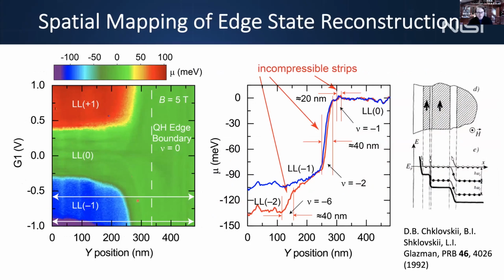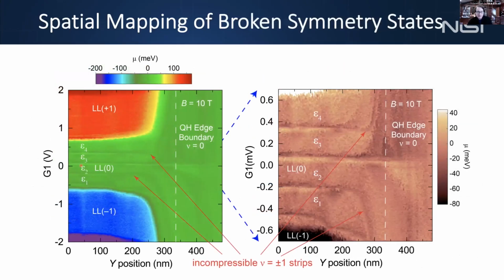If we cut across here, we can get the chemical potential profile shown in the middle here. And you can see it has that same step-like staircase we saw in the Landau levels. So this is, again, another measure of that reconstructed potential, now directly measuring the chemical potential. So you have the compressible regions, the incompressible strips, and then you can calculate what you'd expect from this paper here, and you can see that you get fairly good agreement with a length scale on the order of 30 to 40 nanometers.